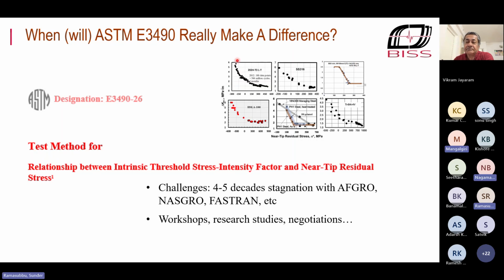Okay, so that you can modulate, and it doesn't depend on the material as long as you have this property. The other good thing about this property is that we haven't seen a huge difference on the 7075. We did this work with Vikram, Praveen, and their PhD students some time back. We had a 7075 plate, 50 mm thick, and we found the properties on that one, and then sliced it to get just 5 millimeters, and again found the properties, and they were more or less one and the same, which is not what you will find with crack closure, because crack closure is sensitive to stress state.